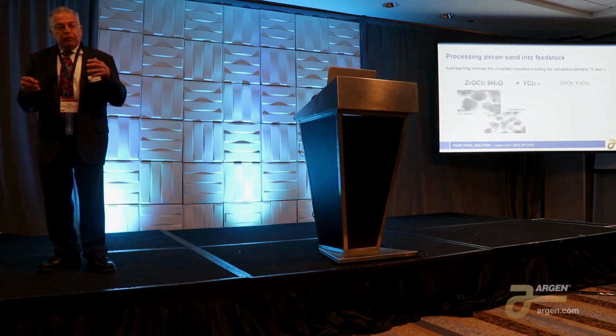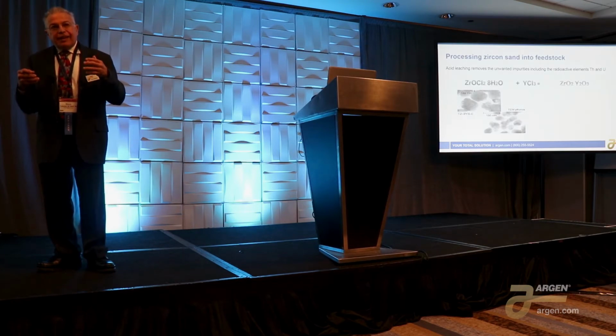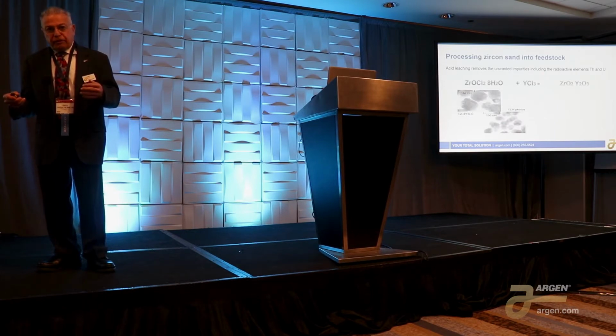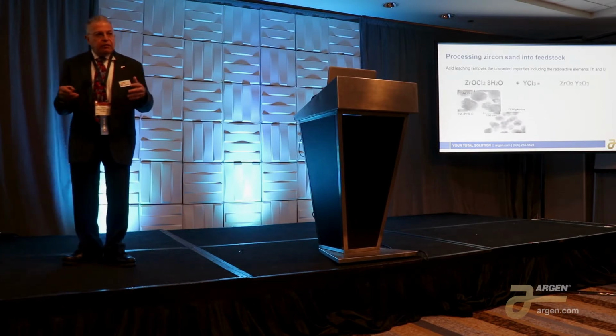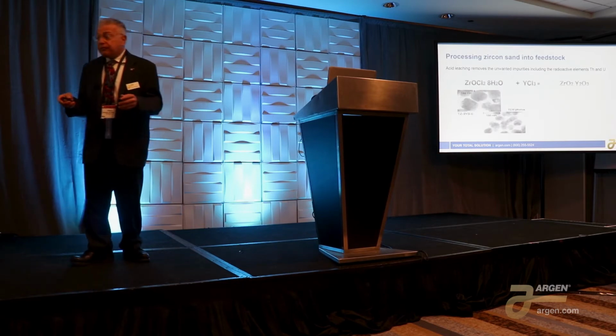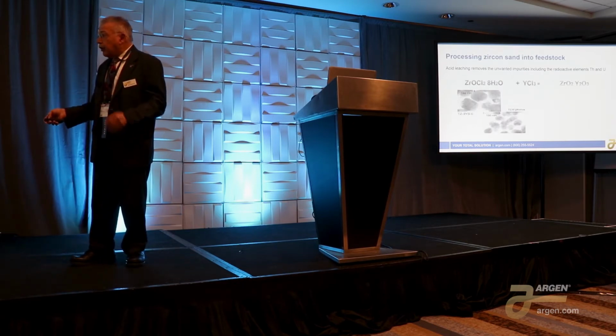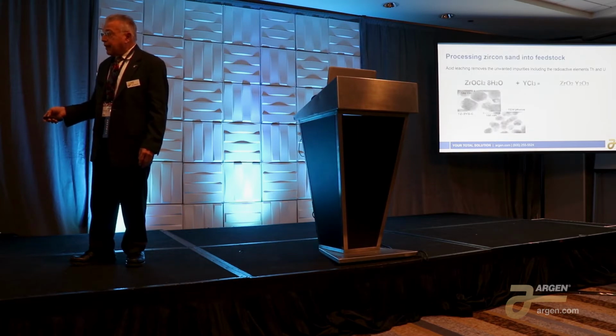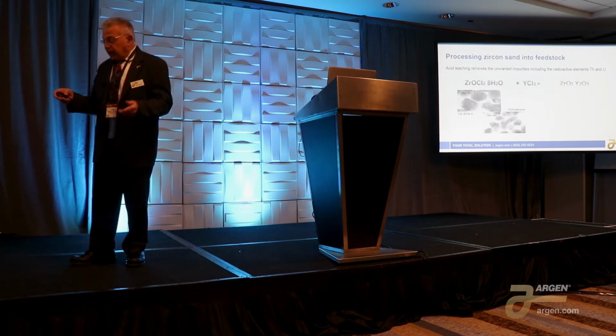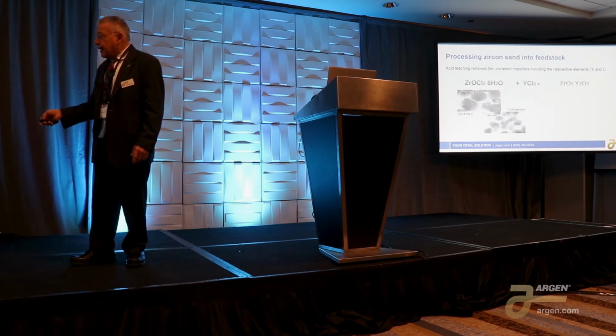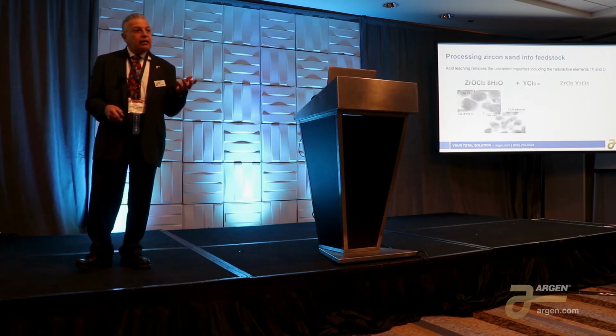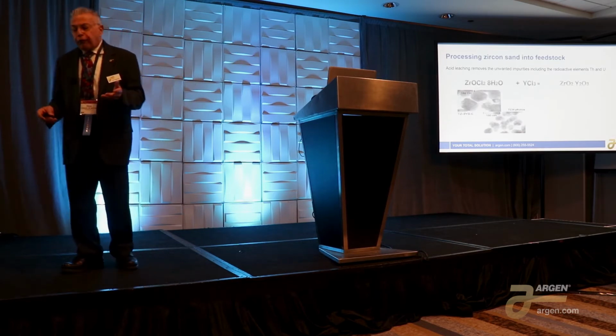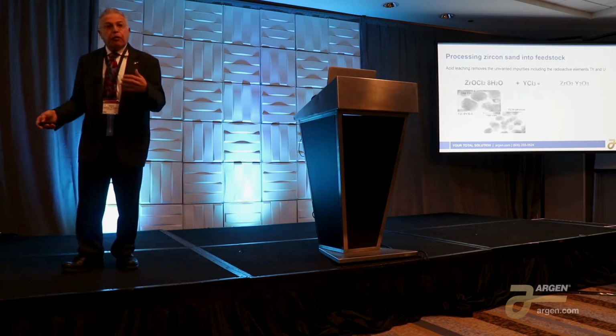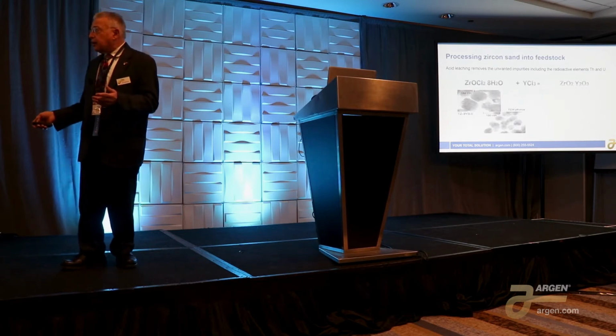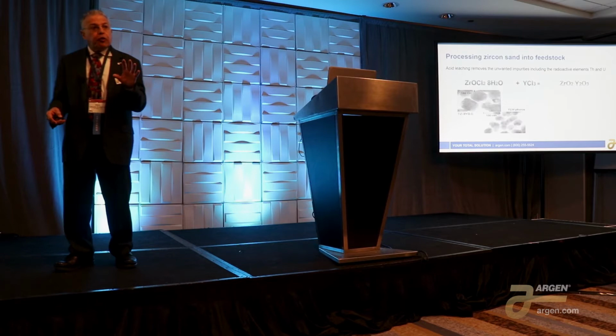And as a dental material for prosthetics, it's very unique in that the processing of the material determines the properties of the material. And you'll see in a minute, with other materials that we're used to, that's not the case. So here we can have large crystals, and we could take that liquid and mill it and make the crystal smaller. And if we do that, we're actually going to impact the optical properties of the material. The finer crystal materials will actually develop a more opaque material than the larger crystal materials. So we have to control that crystal size.